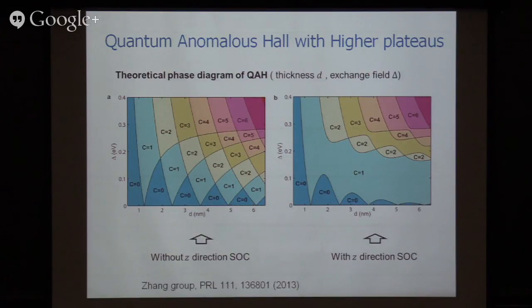A very interesting thing we observe is that as a function of thickness and the amount of magnetism, or the size of the exchange gap you put into the system, there are actually many possibilities. You can be at Hall plateau 0, 1, 2, and so on. But here, notice there's an interesting development: as I increase the size of the ferromagnetism in the sample, I go to higher conductance.